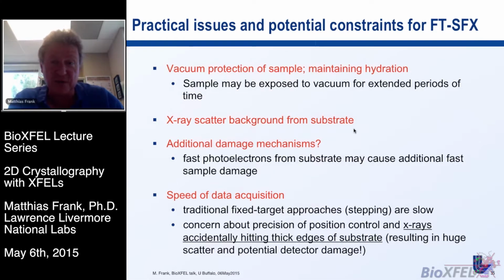There are some practical issues with the fixed target approach, and foremost, the vacuum protection of the sample. If you have a sample that needs to be hydrated, if you put that on a solid substrate and put it in vacuum, it will dry out very quickly. So you need to think about how to protect your sample from vacuum. The extra background from the substrate, while I said it's not as bad as for LCP, could be an issue if you have very small nanoparticles or if you want to go to single molecules.